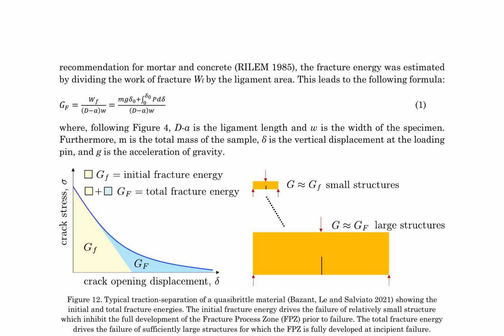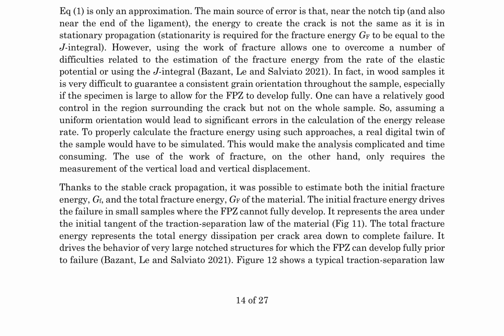The primary source of error lies in the difference in energy required to create a crack near the notch tip versus during stationary propagation. In wood samples, estimating fracture energy is further complicated by the challenge of guaranteeing a consistent grain orientation throughout the sample. Assuming a uniform orientation would lead to significant errors in calculating the energy release rate. In contrast, the work of fracture approach only requires measuring the vertical load and vertical displacement.